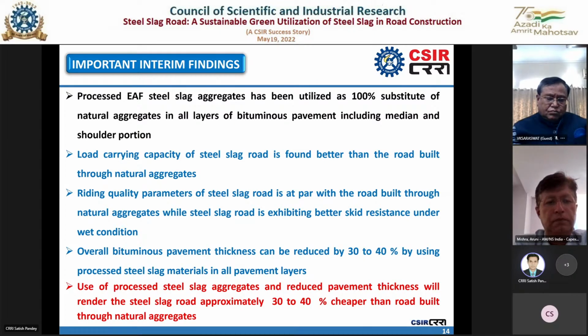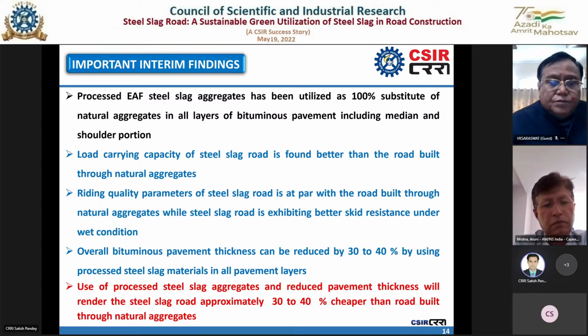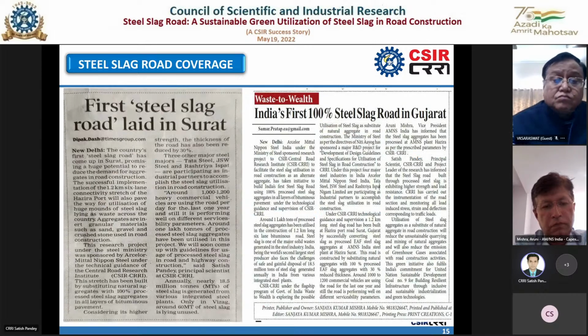The overall pavement thickness can be reduced by 30 to 40% by using processed steel slag material in all pavement layers. And one of the most important benefits is that use of processed steel slag aggregate with reduced pavement thickness will render the steel slag road approximately 30 to 40% cheaper than the road built through natural aggregate in that particular region. So this is a glimpse of some of the media coverage carried out in various leading newspapers.